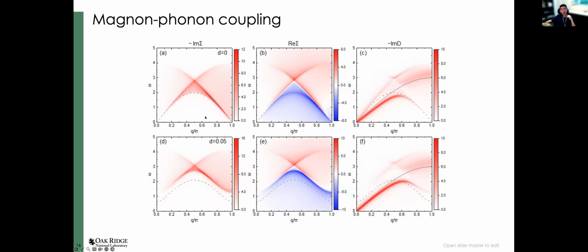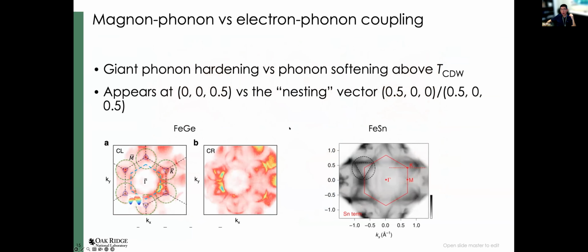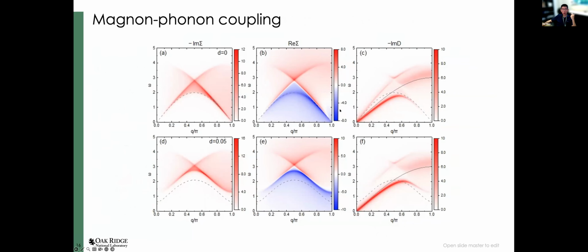So motivated by these observations, we started to calculate the phonon self-energy effect. Here we show the calculated imaginary part, real part, and dynamic structure factor. The dashed line corresponds to a magnon excitation, and the solid line corresponds to a bare phonon excitation. You can see that by considering the magnon-phonon coupling, you already see the phonon broadening and hardening effects that are qualitatively consistent with experiment. But I have to emphasize, this is a very simplified model that does not consider the more complicated magnetic structure and phonon structure. So to us, a qualitative agreement is expected rather than a quantitative agreement.